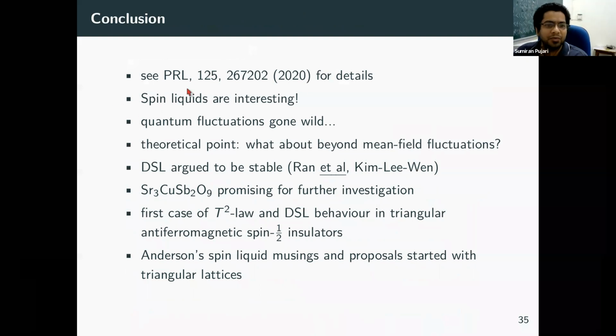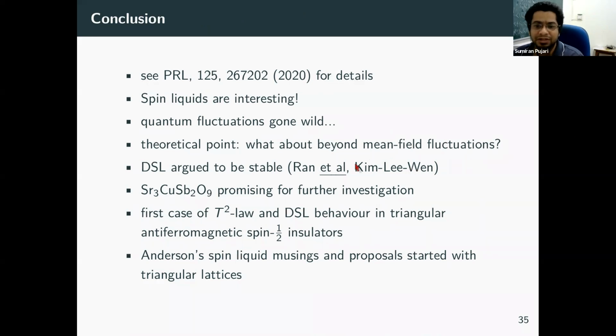This is where you can find more details, but I hope to at least convey to you that spin liquids are interesting in the sense that this is really where quantum fluctuations have gone wild. And one theoretical point that I didn't cover is that, for a mean field to be a good description of your material, the beyond-mean-field fluctuations have to be small so that the theory remains well behaved and consistent. It turns out that this Dirac spin liquid theory has been argued to be stable, but this is a little bit of an exotic argument. But I believe this material is promising for further investigation.